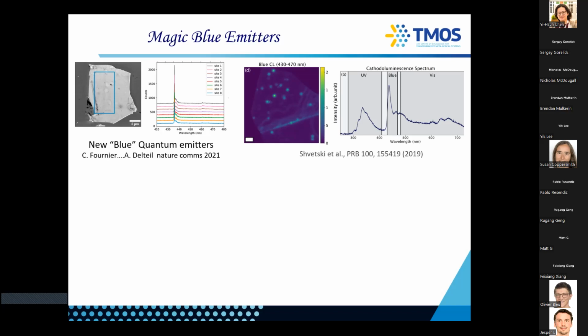As you probably gathered by now, our biggest challenge with hBN is that the emitters fluctuate in wavelength. They're all around 600 nanometers, but still fluctuate. And you really don't want that, because you want something focused exactly on the same wavelength to actually design something for them. So we looked back at the literature and saw, wait a second, in 2019, almost 3 years ago, people had already measured these blue emitters, actually randomly. This is from the group of Alex Zettl in an exfoliated hBN flake. So every spot here has a blue emitter. So not always when you read something in a fancy journal that claims something is new, is it actually new. This is more for the students than the rest of us.